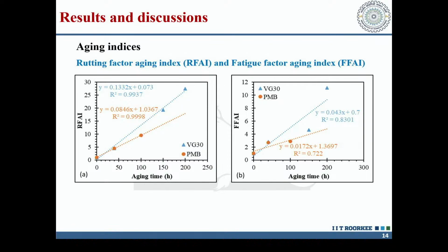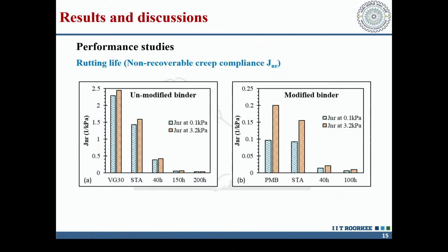This is showing you the rutting factor aging index and fatigue factor aging index. You can see here these values when the aging is less. At that time, there is not much difference between the modified and unmodified binders. But as the aging is going on, the effect is visible there. For the modified binder, the aging is less. Then we have JNR, which is the indicator for the rutting factor, and you will see here it is also showing that for the modified binder, the JNR is better. We have done it as you can see for the short-term aging, then 40 hour, then 150 hour, then 200 hours for the unmodified binder, and 40 hour and 100 hours for the modified binder.